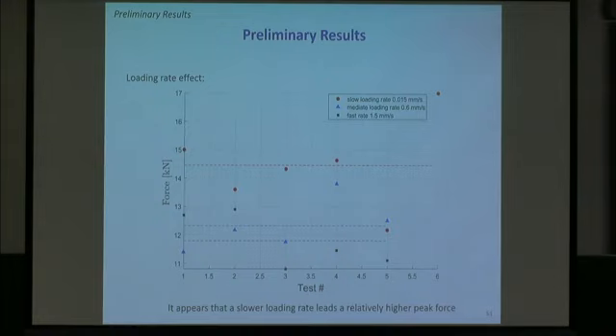And at first I thought maybe this is because of some additional energy dissipation mechanism going on behind there. Like Alan, in his paper, you mentioned that. I think other people also mentioned that if you load fast, you get a relatively lower force. If you load slow, you get a higher force. But you are talking about fracture toughness in that paper, and this is something we got from what we measured.